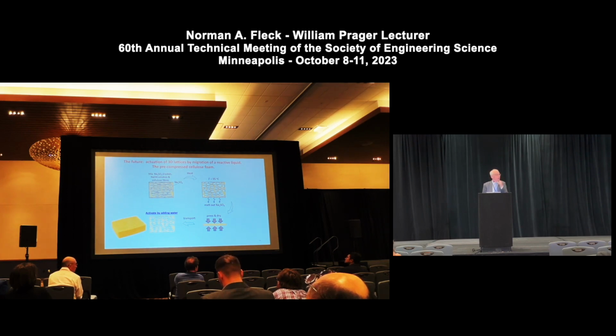So this is the commercial way that cellulose foams are made, and then often they're transported and sold in this form. You take cellulose fibers, you add sodium sulfate crystals, which define the cells, this three-dimensional foam. You melt out the sodium sulfate crystals and then compress and dry the structure. And you end up with something which looks like cardboard, cellulose cardboard structure, but actually it's got compressed cells in it. Then, once you ship it and add water, it activates.